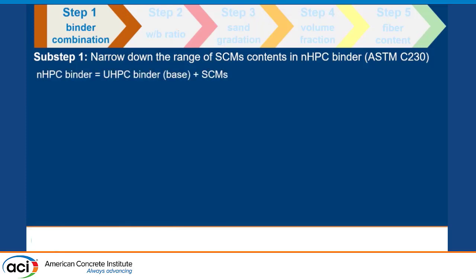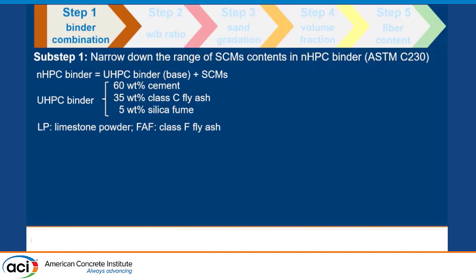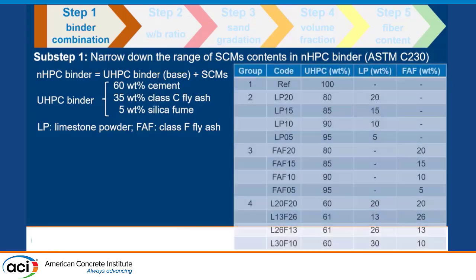So the first thing in step one is to narrow down the range of SCMs in our nHPC binder, which employs the UHPC binder as a base and multiple types of SCMs in it. The UHPC binder in our study has a fixed amount of Type I/II Portland cement, Class C fly ash, and silica fume, and limestone powder and Class F fly ash will be used as the SCMs. So we have the table of the groups that we are going to use to first narrow down the range. The maximum substitution of the SCMs, limestone powder and Class F fly ash, is 20%.